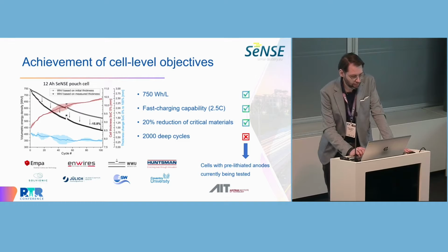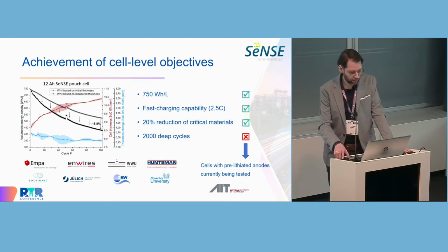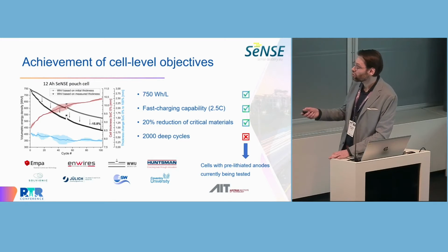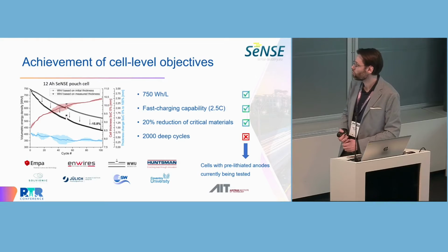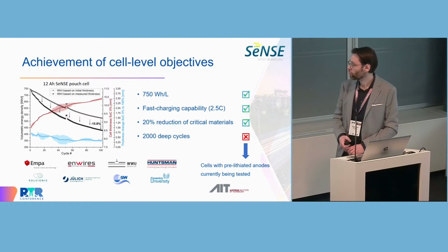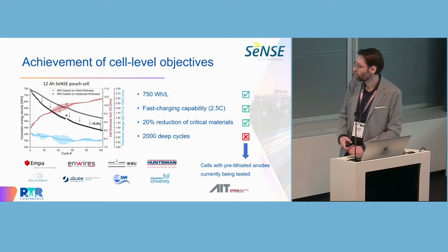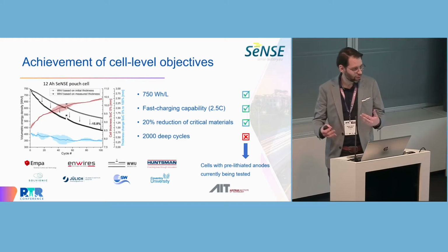Maybe looking a bit at the achievements of the cell level objectives that are listed before. So we actually managed to achieve this quite challenging energy density target of 750 watt-hours per liter. Also, in terms of fast charging, we are relatively good. We managed to reduce the content of critical raw materials by 20%. But in terms of cycling stability with silicon, as Boshida also mentioned, this remains really a challenge.